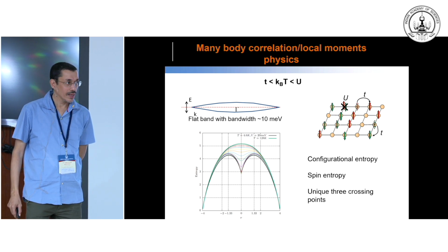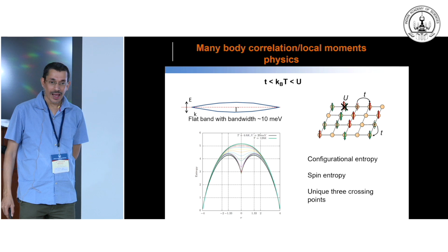I mean, think of this as a lattice. In the flat bands, they cannot be localized at one site. I mean, unless you are looking at a real space picture, the band states will be along those ridges which separate your AB and BA stacked sample. Oh, you are saying the domain wall. Yeah, domain walls. Has someone looked at it? I don't think it's localized.